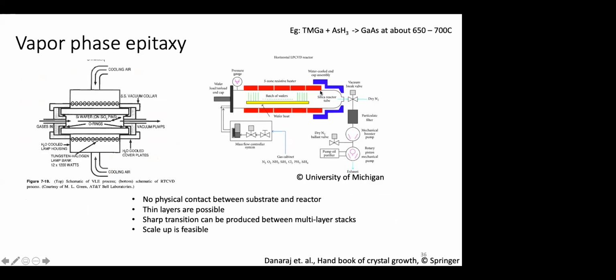Another way to do it is called vapor phase epitaxy. Instead of having a melt, you send different gases. For instance, if you want to grow gallium arsenide, you send trimethyl gallium and arsine. AsH3 is arsine. If you want to grow aluminum gallium arsenide, you send trimethyl gallium, trimethyl aluminum, and arsine. So you have different gases. You send them through. You maintain a particular temperature, and then you grow this material on top of the other. In vapor phase epitaxy, you have no physical contact. You can grow very thin layers. You can have sharp interfaces.